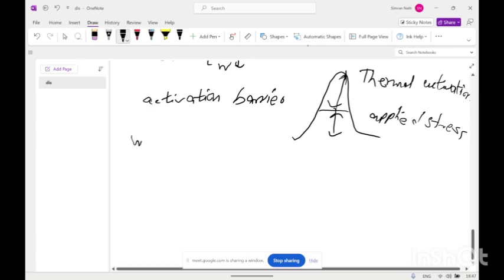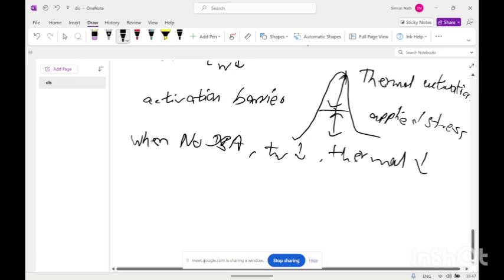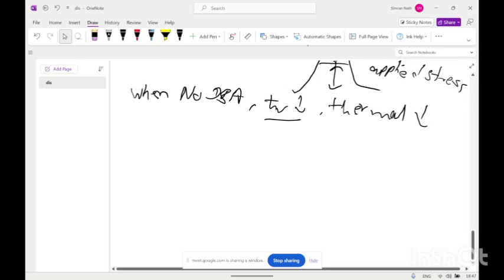So when there is no dynamic strain aging, the waiting time of the dislocation is very less, and the thermal activation provided for the dislocation is also less. Because of the decrease in waiting time, more stress has to be applied for the dislocation to move.